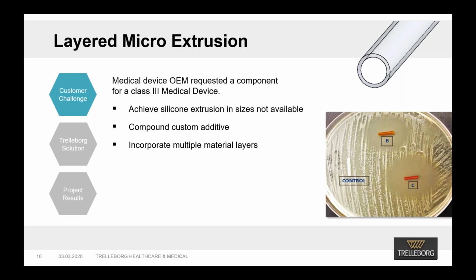From a process perspective, the challenge of this customer's request included the balancing of very high pressures between two extruders to achieve precise concentricity between the layers while maintaining dimensional stability of diameters on a scale that requires very high magnification to verify. And then the packaging of a highly static-prone extrudate to avoid damage and tangling during transit. From an application perspective, the concentrations of the additive and thickness of the layers had to be tested to achieve the optimal elution rate for the application.